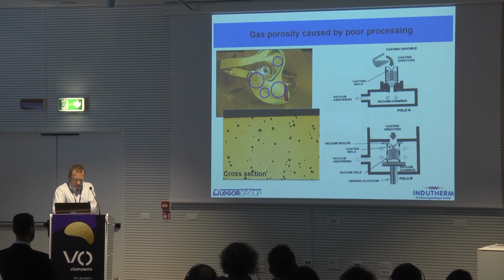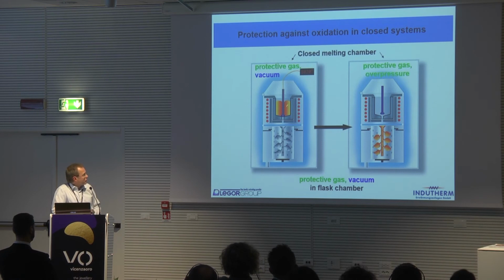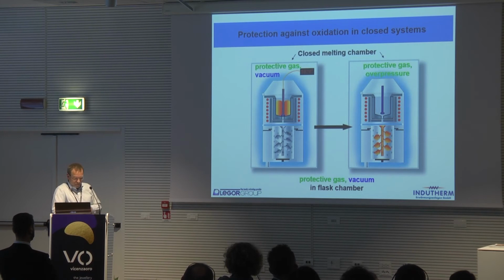So nowadays, we usually work with closed chamber machines where we have a protection of the melt in a closed chamber where we can work with protective gas and vacuum. And of course, we have a closed flask chamber where we can also work with protective gas and vacuum to maintain a very clean atmosphere, an oxygen-free atmosphere during the melting and pouring process.